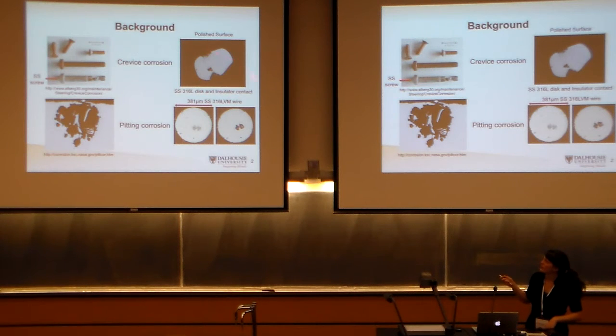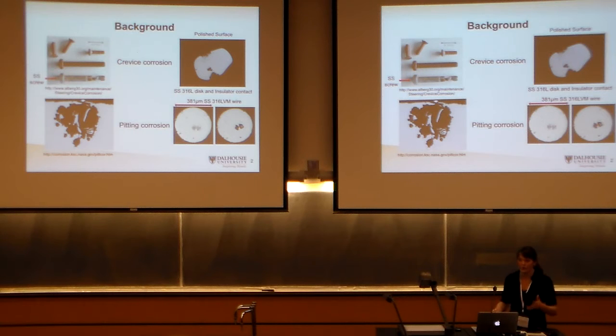And on the right is one of our samples, a stainless steel disc, and here you can see the polished surface where, at the top and the bottom, crevice corrosion has occurred between the insulator that we coat the surroundings with and the surface. Our main focus of our research was pitting corrosion.